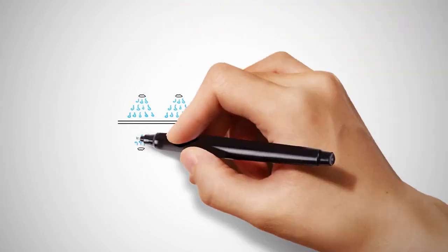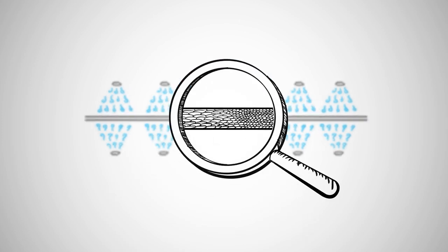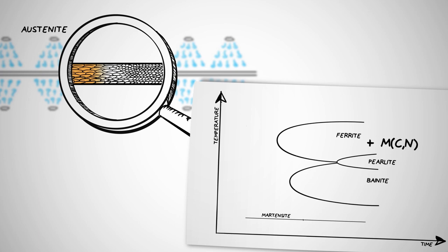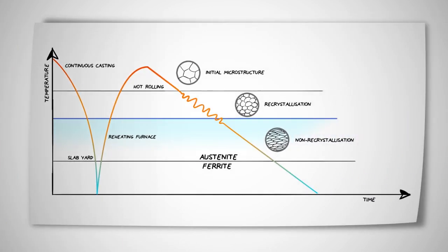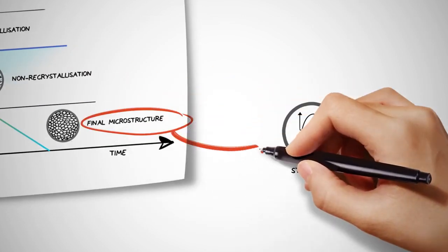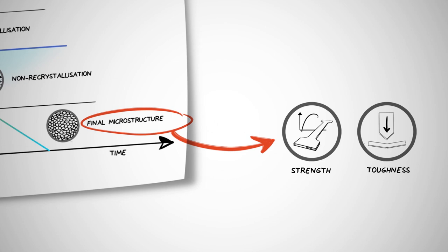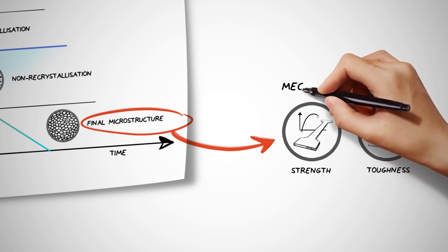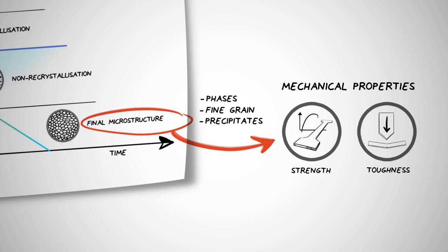In the cooling zone, the structure of the steel is converted from a high-temperature crystalline form known as austenite into a low-temperature form containing ferrite and certain percentages of bainite, pearlite, or martensite. During this transformation, the pancaked austenite grains provide the best possible basis for the creation of a very fine ferrite microstructure. This is the origin of high-strength steel. In addition, fine grain also means first-rate toughness, which is another key feature of API grades.